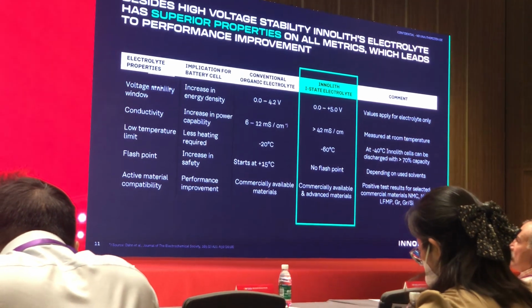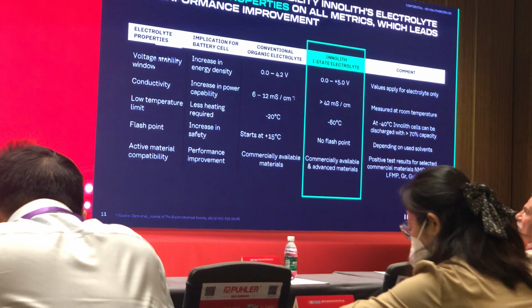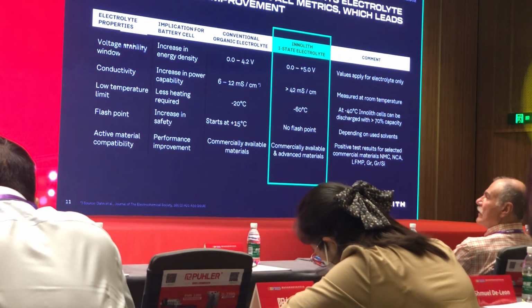And after showing the high voltage stability, we were also investigating the low potential stability, which was also very good. So we could cycle graphite and lithium in a very stable way. We also measured the conductivity, which was a bit lower than what we measured in our first generation, but still good in comparison to organic electrolyte. This is also directly related to the low temperature limit, which was defined as being at -60. So I will show later some data on a real cell. No flash point, because the compounds of the electrolyte are all fully non-flammable. And we could also show stability with all commercially available materials.